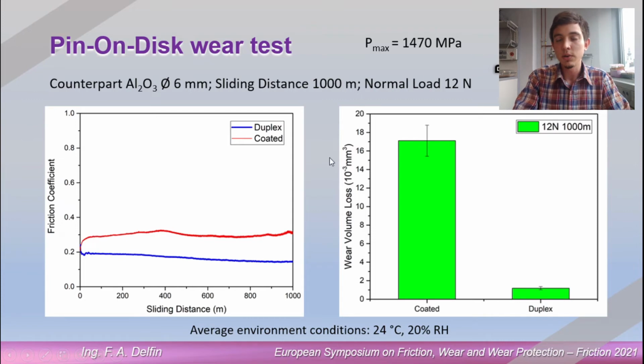Here we see another test because we wanted to check what we were seeing. We increased the load a little bit, only 2 newtons extra, so to 12 newtons, because we have a limitation of the load we can put on the tester, but this was good enough because we appreciate a difference in the friction coefficient now between duplex and coated sample, with the coated sample with higher friction coefficient, also the duplex sample with a slightly higher friction coefficient. This also might be due to different ambient conditions compared to the last one.